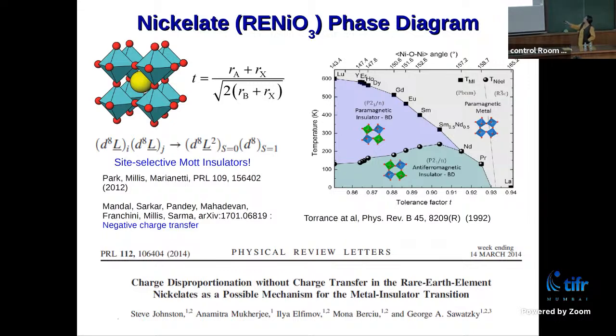Tolerance factor is nothing but a geometrical factor, which is defined in terms of the ionic radius of the A cation, B cation, and X, which actually means oxygen. Depending on the tolerance factor, because by changing the rare earth you are basically changing the cation size at the rare earth side, this is the kind of tolerance factor versus temperature phase diagram. What you actually get below a certain temperature for most of them, except lanthanum, is a metal to insulator transition, and sometimes together with a magnetic transition.